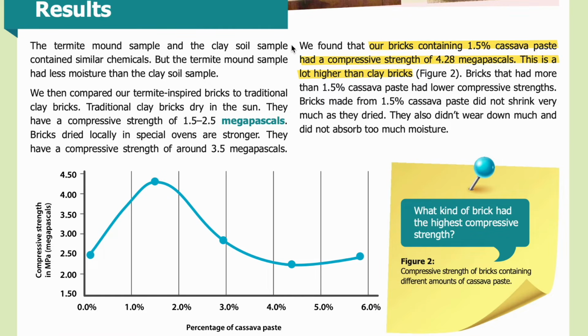Results. The termite mound sample and the clay soil sample contained similar chemicals, but the termite mound sample had less moisture than the clay soil sample. We then compared our termite-inspired bricks to traditional clay bricks. Traditional clay bricks dry in the sun. They have a compressive strength of 1.5 to 2.5 megapascals. Bricks dried locally in special ovens are stronger. They have a compressive strength of around 3.5 megapascals.